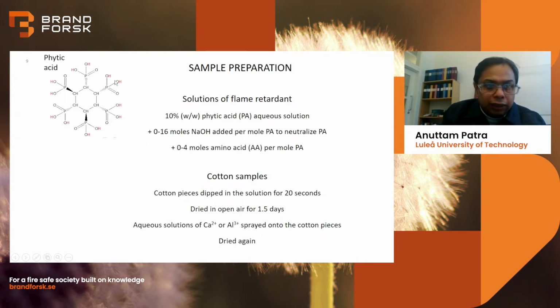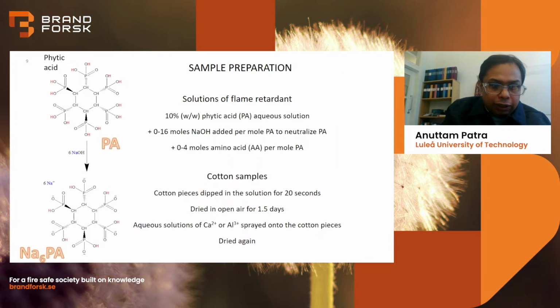As Anakarin showed, it is a 6-member carbon ring. Every carbon is connected with a phosphate group, and there are 12 acidic hydrogens in red color, which means it can react with 12 moles of sodium hydroxide alkali. And for example, if it reacts with 6 moles of sodium hydroxide, then 6 of the 12 hydrogens get replaced, and we call it Na6PA. If it was 3 moles sodium hydroxide, 3 of the hydrogens get replaced, and we call it Na3PA. So we follow this convention.